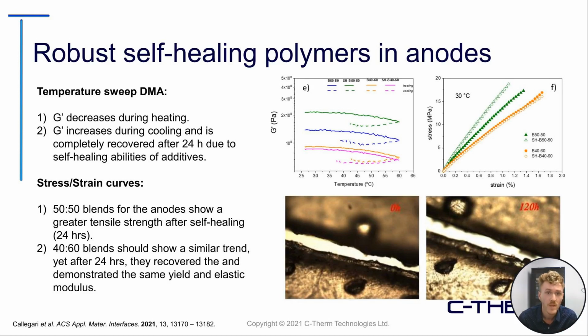By doing stress strain curves and some cutting experimentation and looking at the way these materials self-heal, they're able to show that both 50-50 blends of these polymers have a higher tensile strength after self-healing, but the 40-60 versions of these anode type materials just maintain the same modulus over time, showing how dramatically improved these mechanical behaviors are compared to the existing technology.